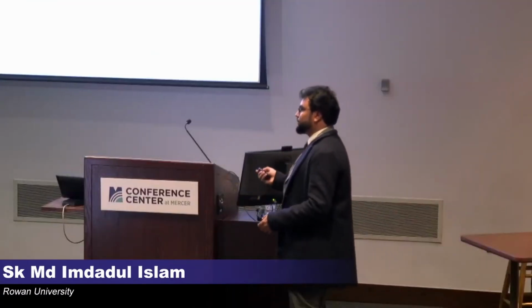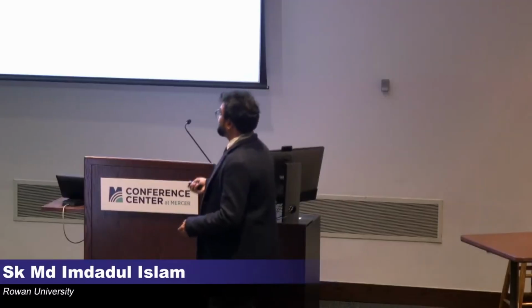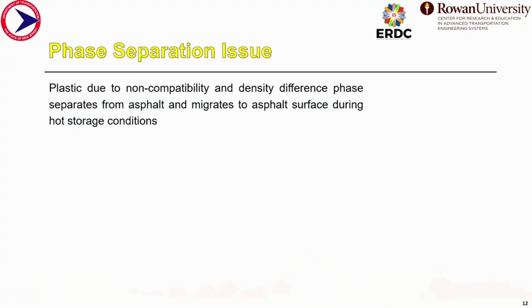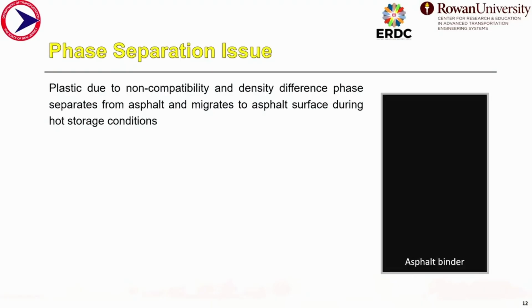So now, why should we care about the phase separation issue, and what is it? Due to the incompatibility and the density difference between the plastic and the asphalt binder, the plastic, after pouring into the asphalt binder, tends to go up to the surface of the asphalt binder at the time of storage. If we see an animation to better understand this, imagine that this is asphalt binder in a tin. When we pour the shredded waste plastics into the asphalt binder, after the time of storage, they tend to go up as the density of the plastic is way lower than the asphalt binder. So this problem is called the phase separation issue in the wet mixing method.